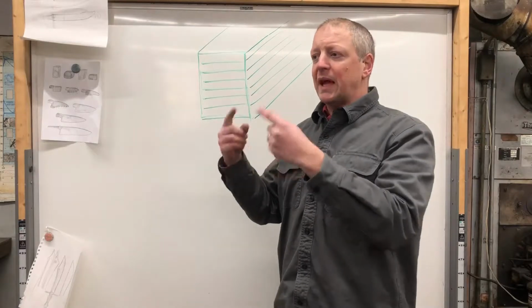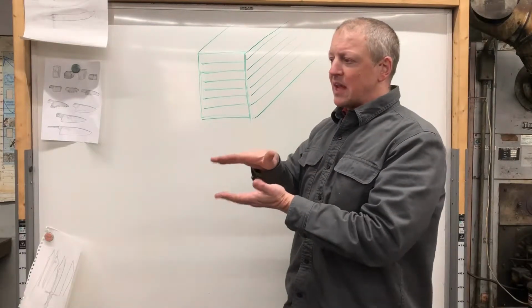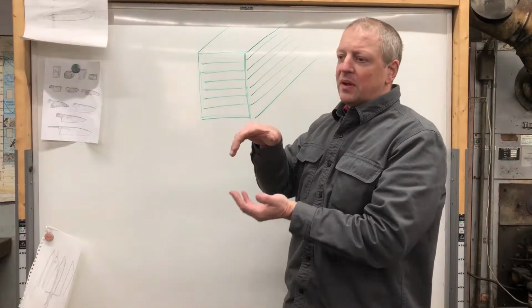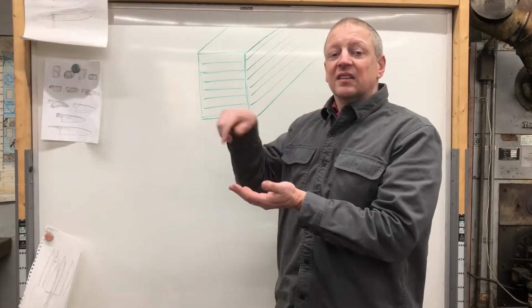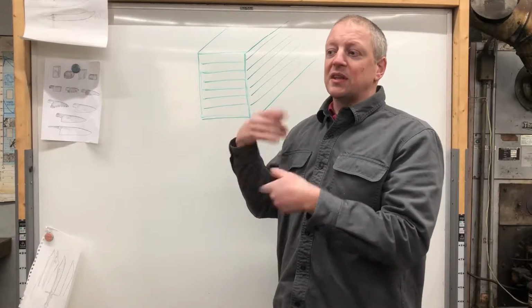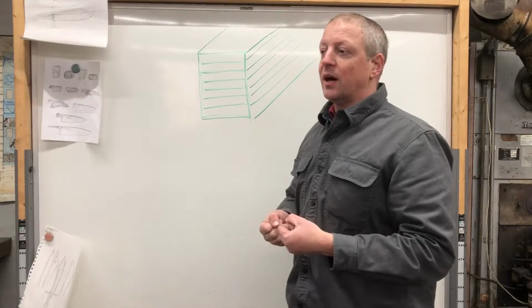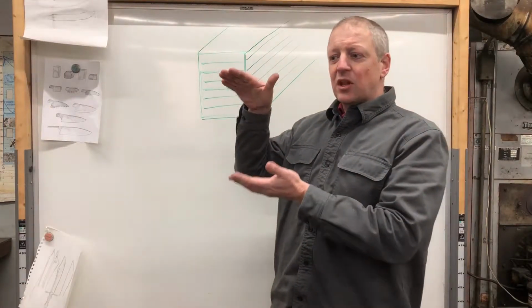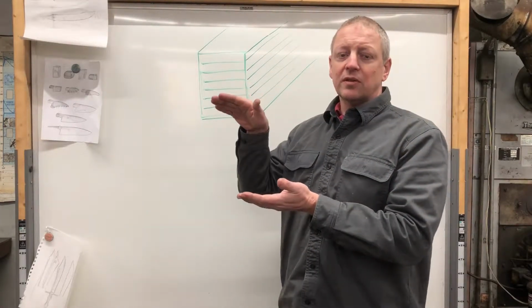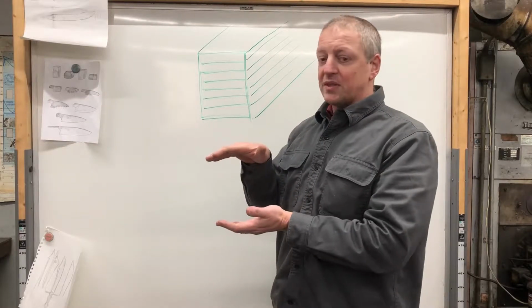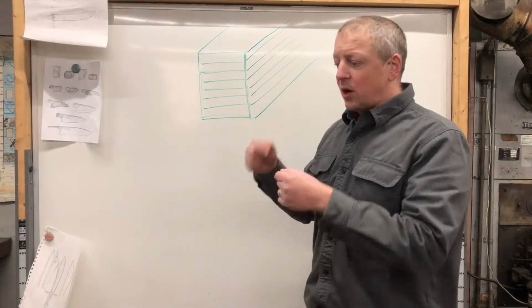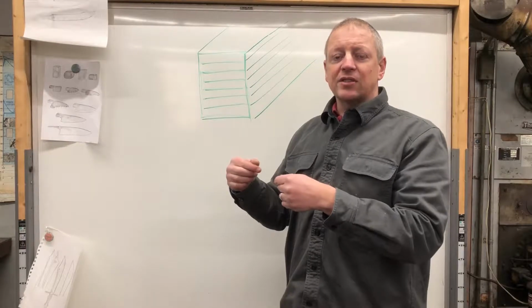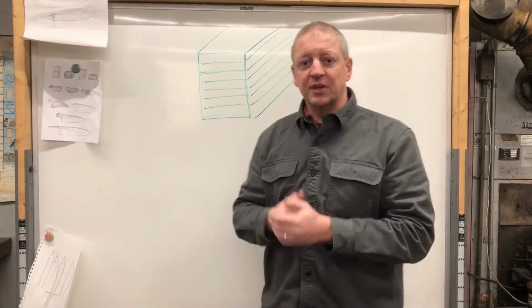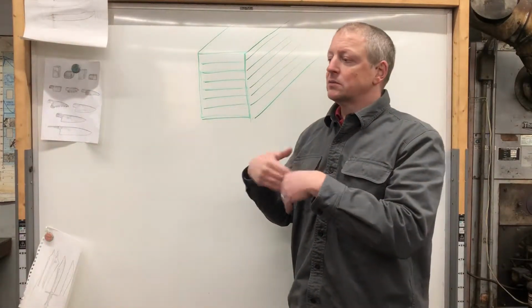If you don't put that extra weld in there, what will happen is as those outer layers heat up, they'll buckle away. That obviously creates big airspace in there. You get a lot more oxidation. Plus, it slows down heat transfer through the whole billet because you've opened up this airspace. So throwing those TIG welds down the side is really helpful in holding everything together.